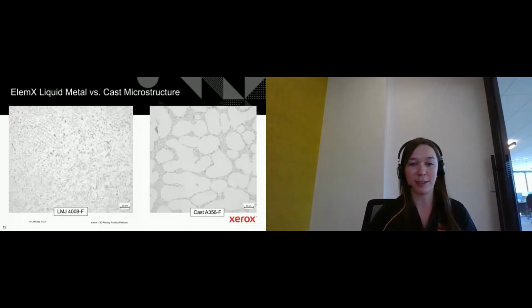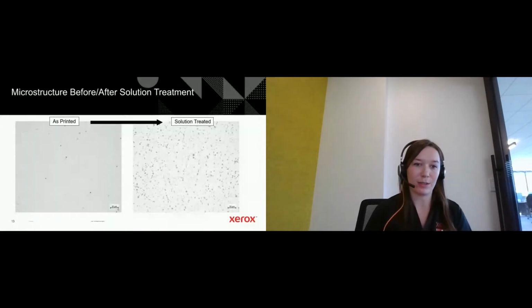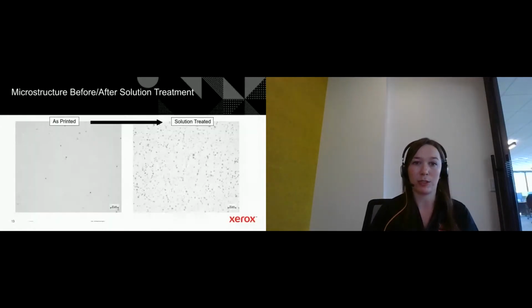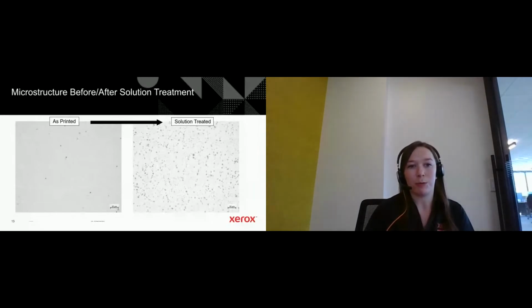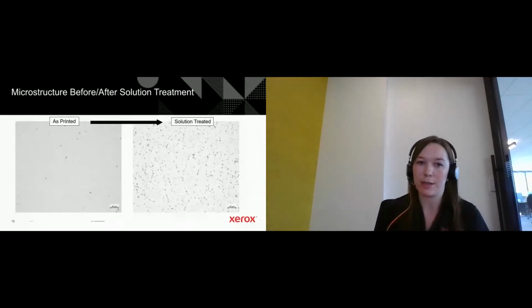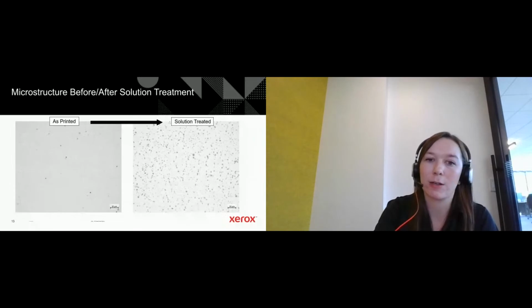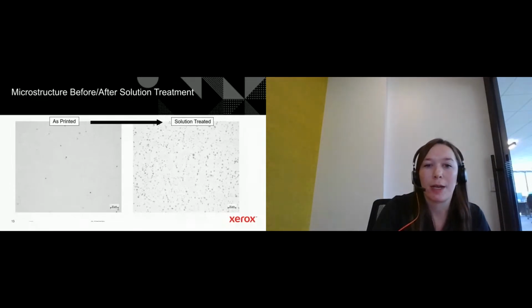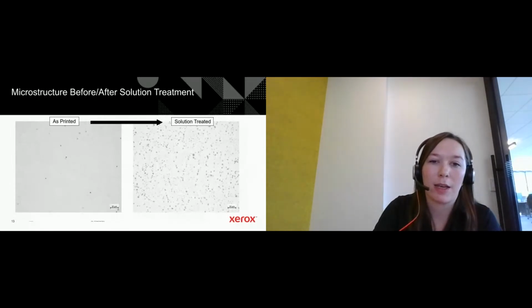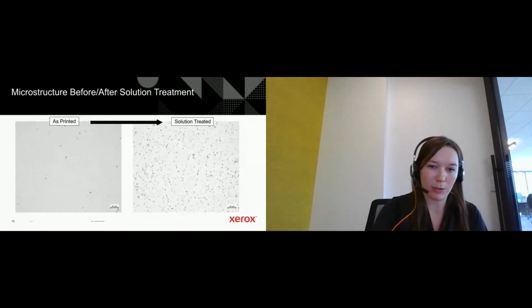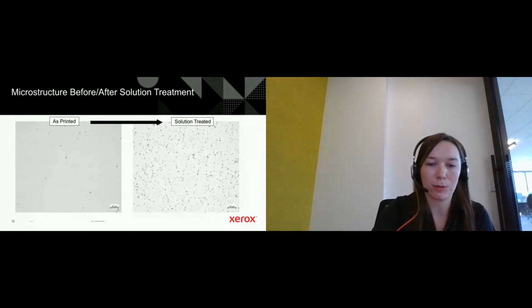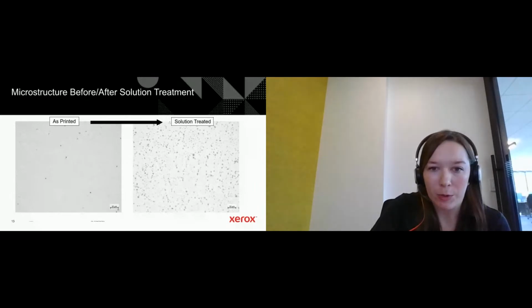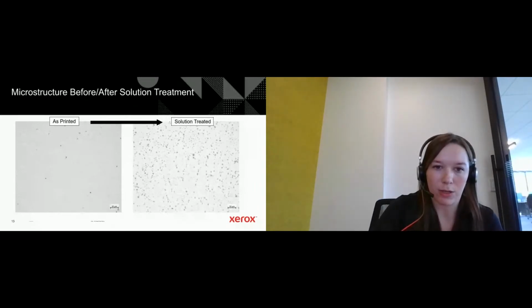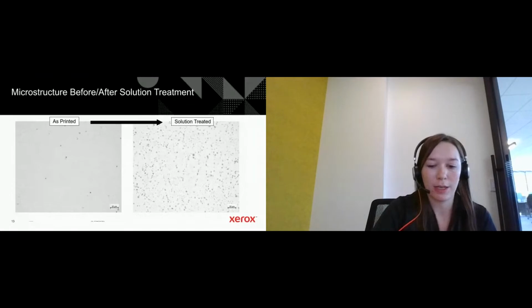However, I hinted at the fact that these parts are typically used in a heat-treated state. So when we do heat treat it, you can see that our microstructure coarsens itself, and this is very typical. And it's still very well dispersed, all the silicon particles. You also see that some of the particles have become more rounded, and this also lends itself to some strength.